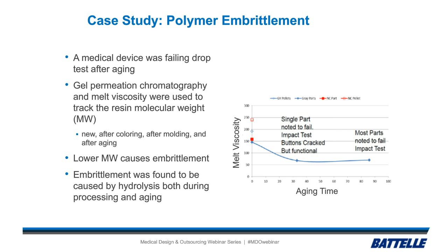before and after aging. And it wasn't all that much, so we thought back and we said, what else is happening to this material before it gets to the aging process? So we looked back, and it turned out that there was a separate step for coloring. So the resin gets made, then it got colored, which was a hot process. Hydrolysis happens faster at elevated temperatures. So there was a coloring, and then there was an injection molding. So there were two steps, and those are both on the little chart there, and you can see how much the molecular weight or the melt viscosity decreases after each of those steps.